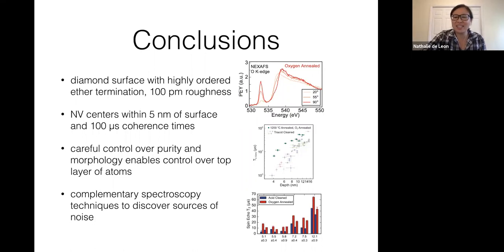Right. So the reason that the coherence time drops as you come close to the surface is because you have magnetic noise from defects at the surface. So what you should see, if we went to much larger depths, which Anya Jayach's group has done with their scanning measurements, then you can see that around 100 nanometers, this sort of levels out because you're mostly just probing bulk noise at that point.